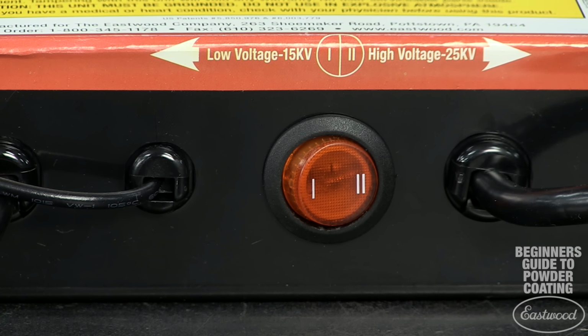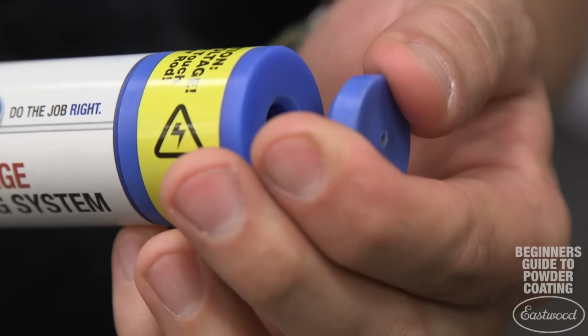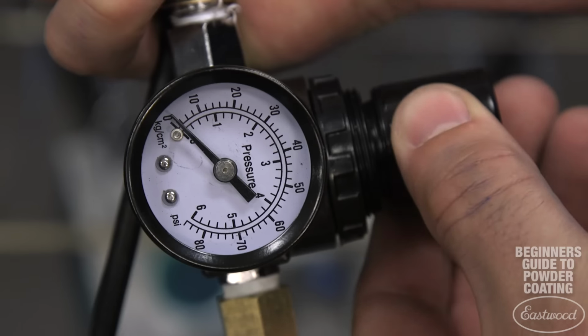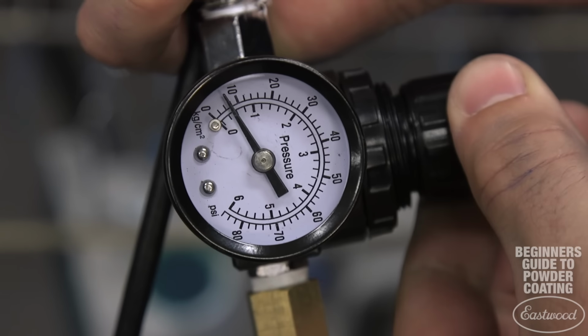To avoid this effect, first set the powder gun to the lower voltage setting to limit the charge you're building up on the part. Make sure you have the deflector on the gun and turn up the air pressure to allow more powder to flow out of the gun.